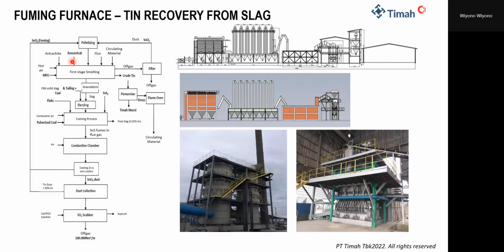In the reverb, the process is reduction of tin oxide into tin. In the fuming furnace, we react the tin oxide in the slag with sulfide. Here we use pyrite to make tin sulfide. When tin sulfide forms, it will volatilize at the operating temperature in the fuming furnace.